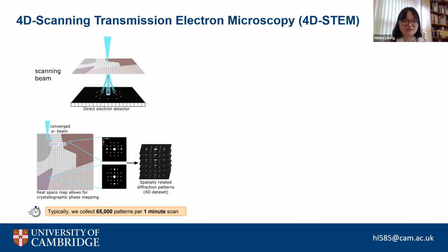So with 3D ED, you had rotationally related diffraction patterns. With 4D STEM, you have spatially related. But you end up collecting far more diffraction patterns than you would with 3D ED because of your probe size, which is much smaller. Typically, in the settings that we use, we collect up to maybe, for example, 65,000 diffraction patterns per scan of an area, which will take about 1 minute for us. And that covers an area on the order of microns.